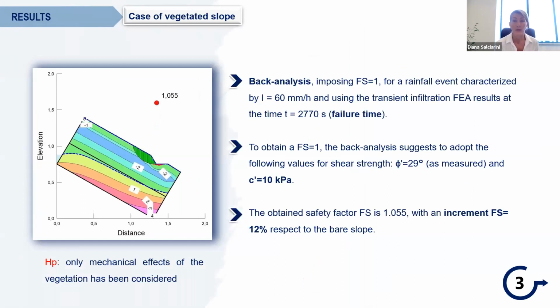As for the vegetated slope analysis, we performed a back analysis imposing a safety factor equal to 1 for the rainfall event with a rainfall rate equal to 60 millimeters per hour, and using the transient infiltration results at the failure time observed during the experimental test. The back analysis demonstrated that to obtain the limiting equilibrium condition, meaning safety factor equal to 1, a cohesion value of 10 kPa needs to be adopted for the tested soil, obtaining an increment of 12% in the stability condition with respect to the bare slope.